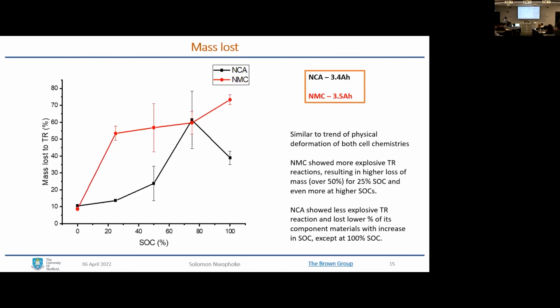I repeated this test up to 4 times to figure out why this happened, but it repeated, and you can see the error bar showing that the chance is quite high that it dropped at 100. I can't really explain why that happened, but from literature, I understand that there is also variation across a given batch of battery. The manufacturer could have some little variation across each cell. So that could be a factor as well.